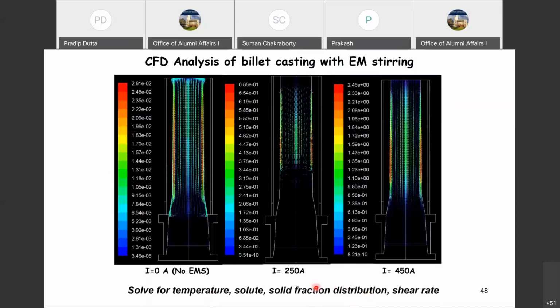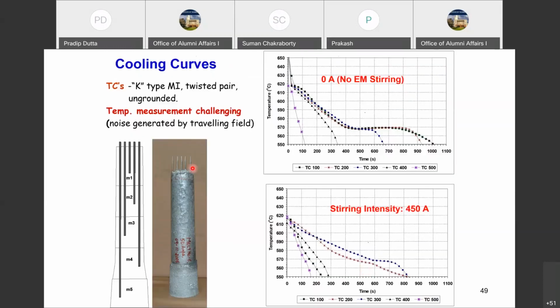And so on, at various current levels. So this is with 0 amperes, means without any electromagnetic stirring, so only natural convection. And these are the ones with the EM stirring at various current levels that we've seen. So finally, we produce such a billet, and we have some experimentally produced ones with thermocouples inserted to record the temperatures at various places. And then we compare those time temperature graphs with our CFD model, and we found them to be satisfactory for various current levels.